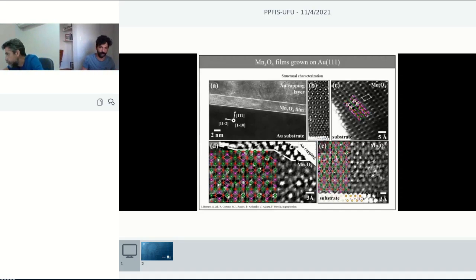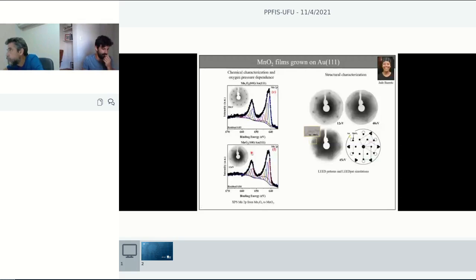Right, so the last type of oxide here that we have investigated is the MnO2 film. This is a very challenging film that we just touched recently with the work of Shadi. You can transform some of these oxide films to MnO2, and MnO2 is very challenging because it can assume a lot of different polymorphs. So then it's hard to obtain this film in a very defined way on a surface. But we had some examples here where we succeeded in doing that.